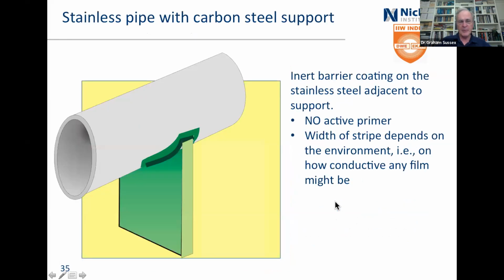And this is an example of that. Here we've got a stainless steel pipe. Here we've got a support, which is carbon steel, painted carbon steel. And so you put a coating around there. But I'm emphasizing no active primer. And the width of the stripe is going to depend on the environment, how conductive any film might be.